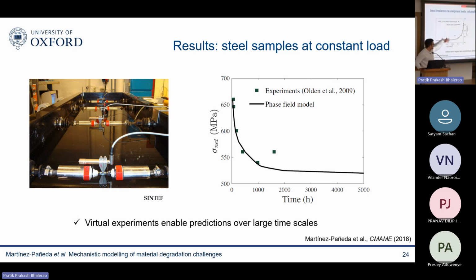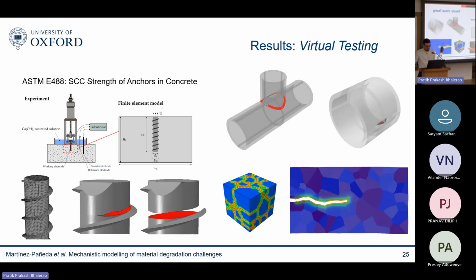But with the model, we can reproduce those experiments in our computer and not only gain confidence by reproducing the experimental data, but also run virtual experiments over very large timescales, very quickly in our computer, very slow in the lab. That allows us to determine what is this critical threshold below which embrittlement will not happen. And you can go up the scales, you can go down the scales as well.